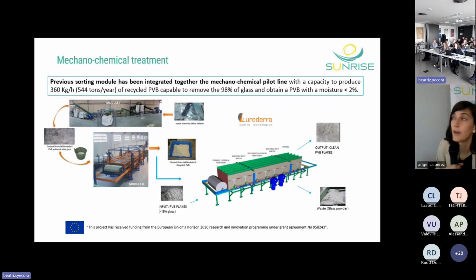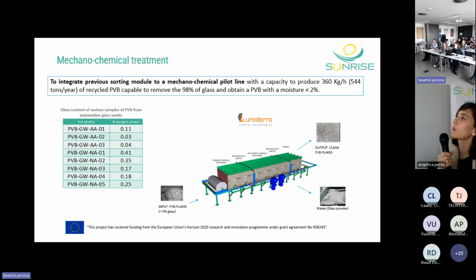The data we have obtained depends on the source of the waste. So it depends if it is construction, it could need further cleaning. But if it is automotive waste, the glass content in the final flakes of PVB is below 0.05%. And if there is aging in the initial process previous to the mechanical process, there is data about below 0.1% of glass.